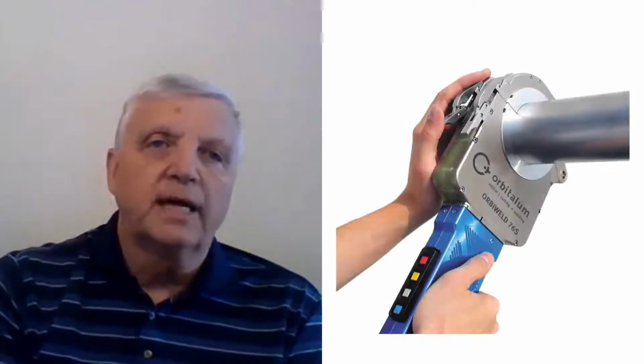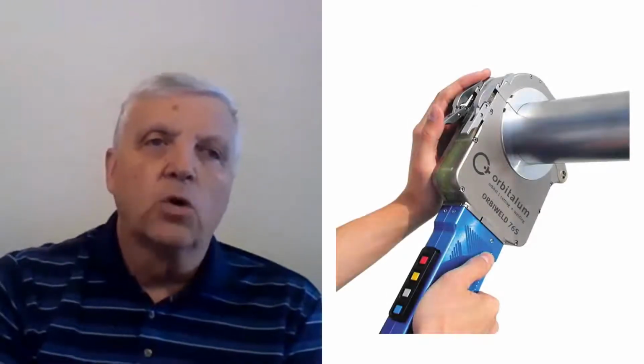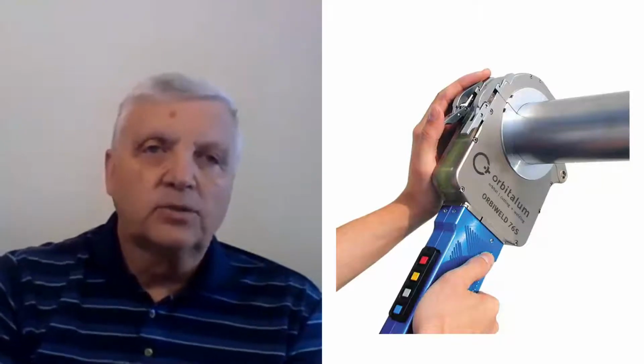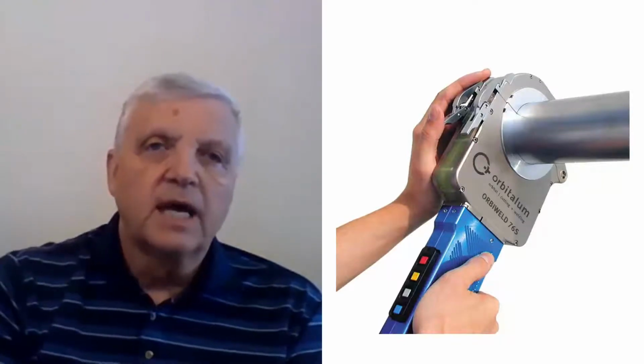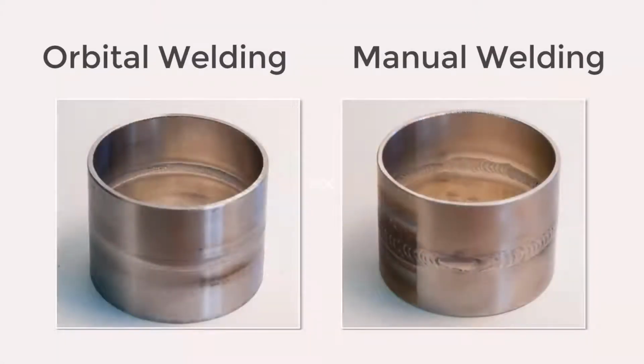In comparison to manual TIG welding of stainless steel tube, orbital welding is achieved with a specialized orbital welding head, which incorporates a clamping device, TIG electrode on an orbital travel device, and a shielding gas chamber. In many cases, a manual weld can look as good as an orbital weld. However, an orbital welding setup can achieve an ideal weld profile consistently with almost complete elimination of weld discoloration.